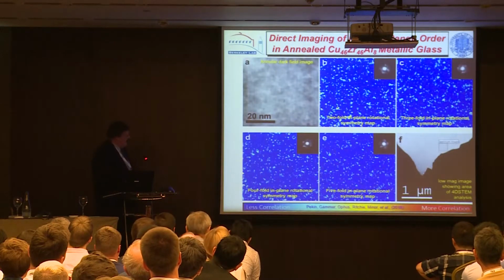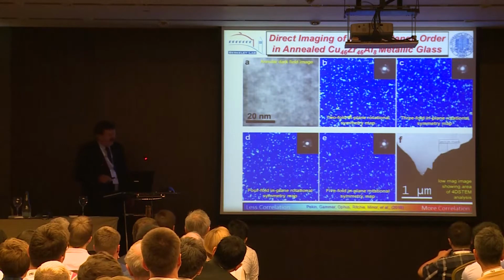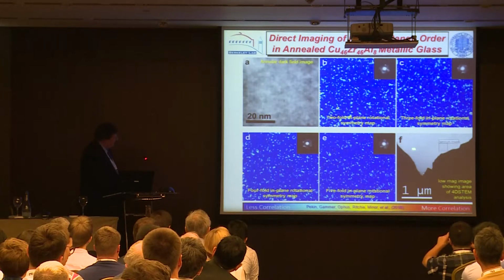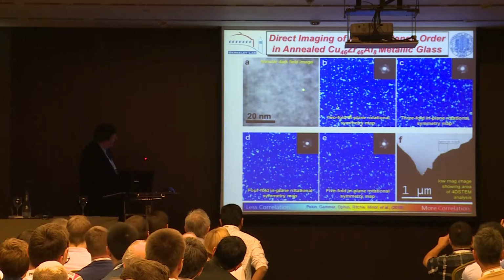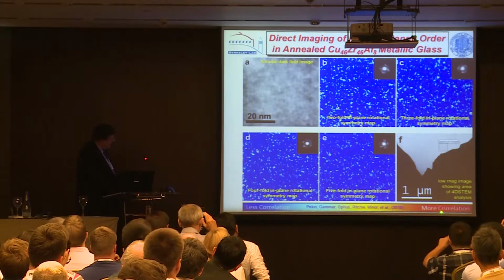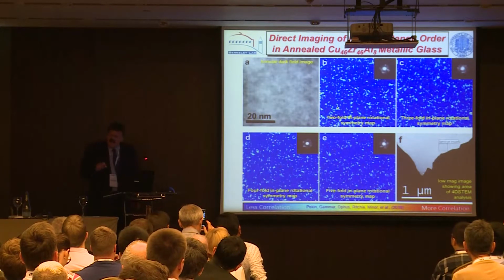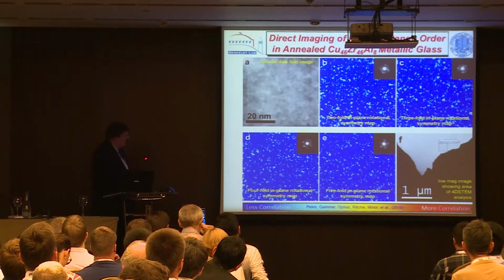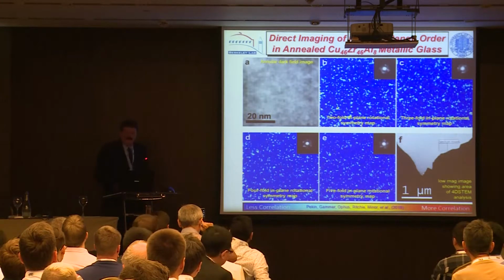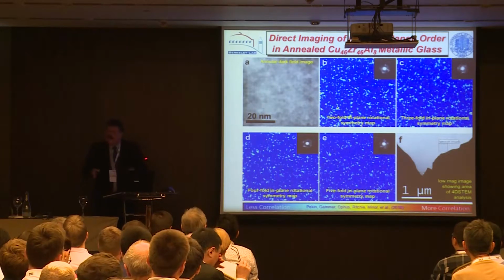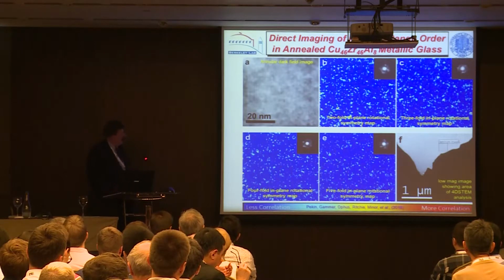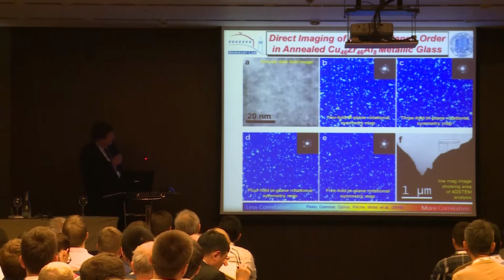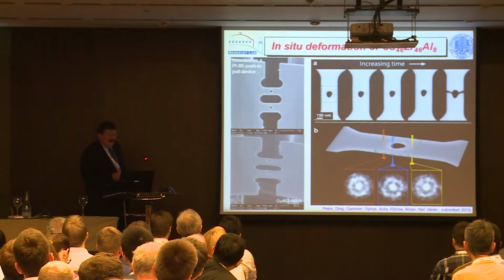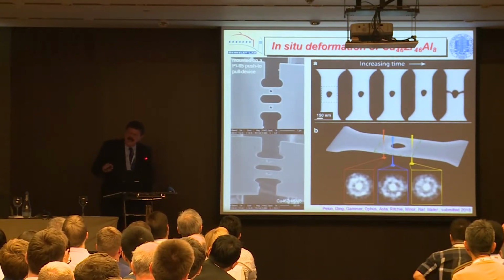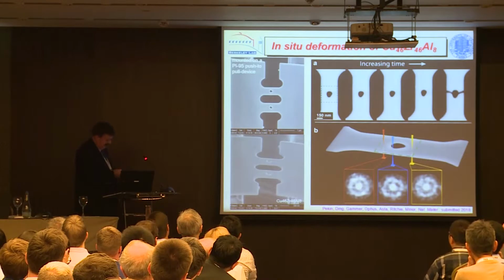This is the first set of data we've generated. It's still rather in its infancy, but what you're seeing here is a simple glass, a little region here, and we've scanned across here. And the colors here, the redder the color, you're seeing a local region of two-fold symmetry, three-fold symmetry, four or five-fold symmetry. So we can start to map out the local order with this technique. This is the first one we've done. And we've also tried to relate this to shear bands, and this is a process that's still being worked on.